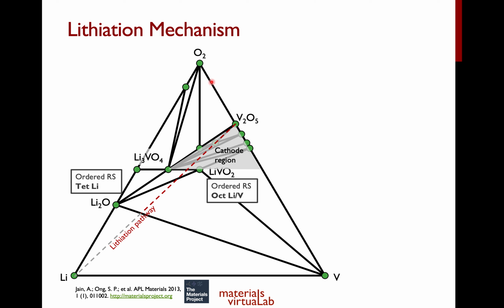Let me first label the lithiation pathway for V2O5. If you start from V2O5 and insert lithium into V2O5, this red line shows you the lithiation pathway. Now, this shaded region over here is what I call the cathode region. This is where Professor Delmar was operating. When you lithiate V2O5 down to this composition over here, you get your Li3VO4, and if you cycle between Li3VO4 and V2O5, you are basically operating within this gray region.